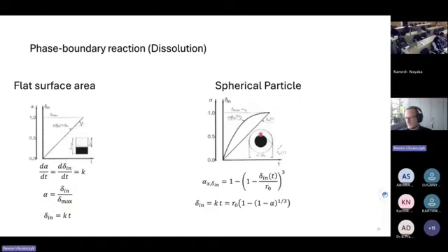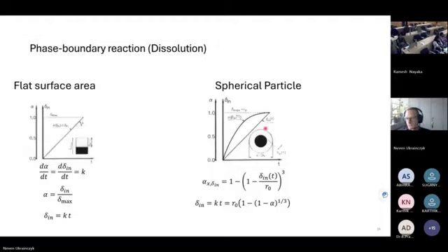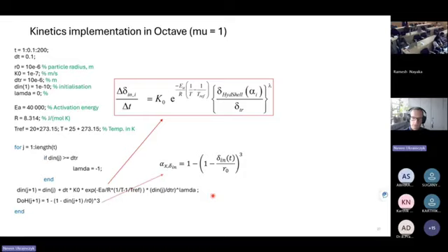But with a sphere you have nonlinear behavior, and from the sphere equation you can easily derive this kind of reaction. You can see it also in the book from Van Breugel. I also put the link here to the thesis of Van Breugel you asked for, where you can download it. So when we do this simple sphere calculation, we can calculate the degree of reaction as a function of the penetration depth.